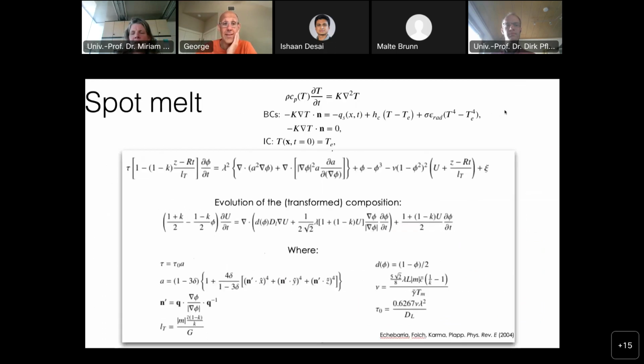Yeah, the physics are two-way coupled in reality, but most people ignore this. Okay. This temperature here is completely decoupled from the phase field, but in reality, there's a latent heat term that, if we do it properly, would be coupled; there would be a phi term here. And then the simulation is much more complicated because they are two-way coupled. But this is not done even in the high fidelity simulations. This term is ignored. The most important coupling is, as I said, that the grains of the previous melt pool affect the grains of the next one. Okay. Yeah, thanks.